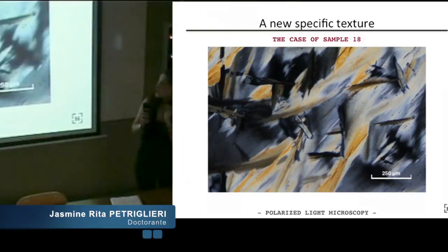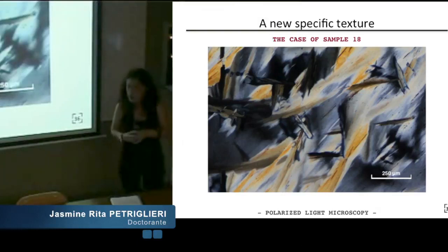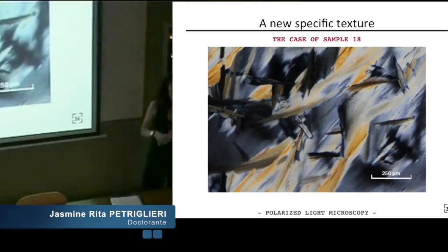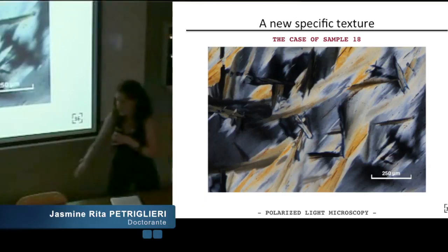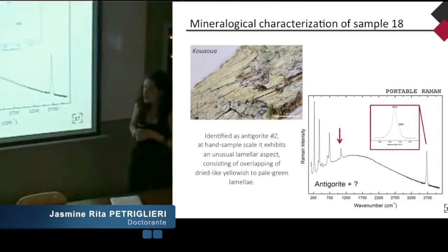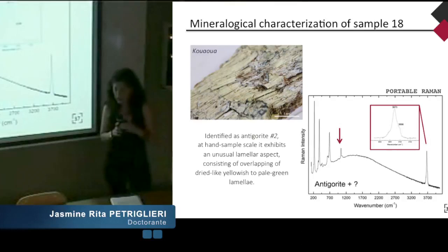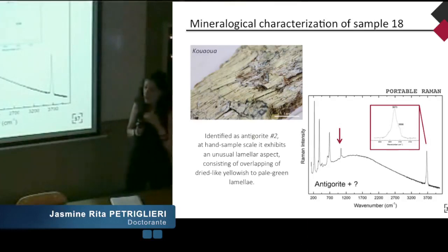So, now let's describe this interesting sample, sample 18, that shows a new, specific and unusual texture. This is an image in polarized light microscopy, a photograph of the thin section, and we can observe unusual star and fan-shaped aggregates. This sample was identified by mine geologists as antigorite, degree of alteration number 2, and at hand-sample scale it exhibits an unusual lamellar aspect that consists of the overlapping of light yellowish to pale green lamellae.